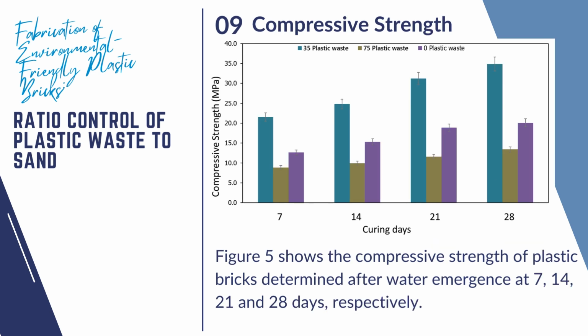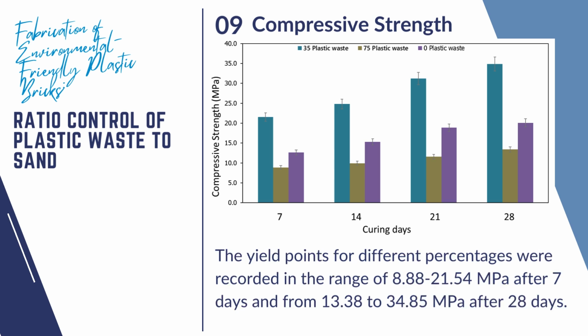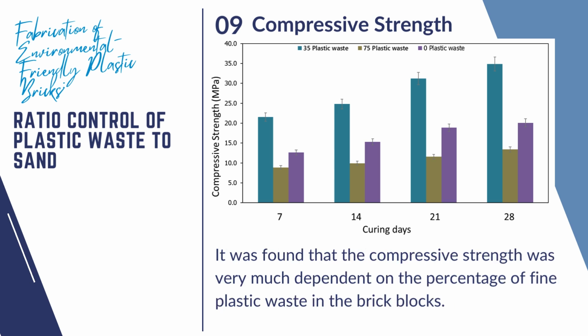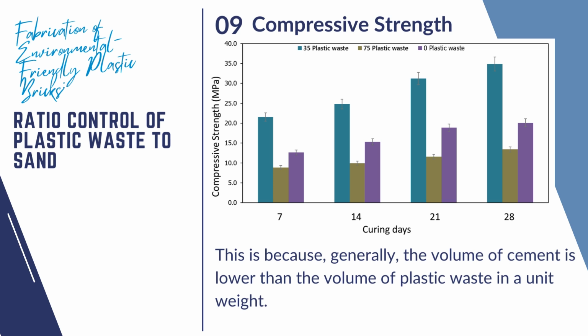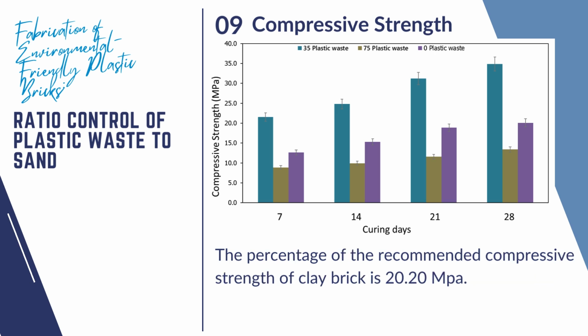Figure 5 shows the compressive strength of plastic bricks, determined after water immersion at 7, 14, 21 and 28 days, respectively. The yield points for different percentages were recorded in the range of 8.88 to 21.54 megapascals after 7 days and from 13.38 to 34.85 megapascals after 28 days. It was found that the compressive strength was very much dependent on the percentage of fine plastic waste in the brick blocks. This is because, generally, the volume of cement is lower than the volume of plastic waste in a unit weight. The recommended compressive strength of clay brick is 20.20 megapascals.